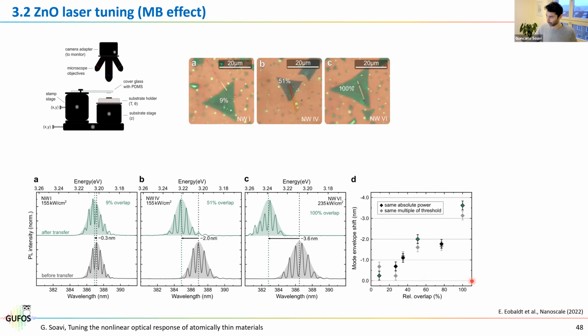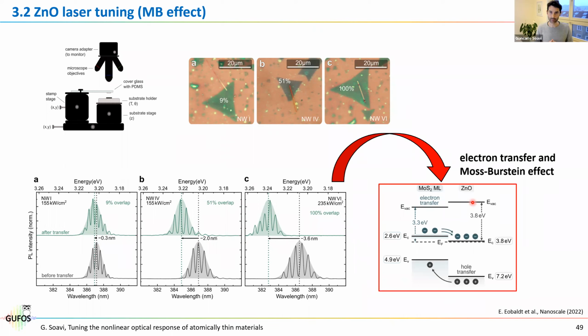Now you can plot the mode shift as a function of the relative overlap of the nanowire and the TMD, and you see that there is this monotonic increase. We were wondering why this happens, and our assumption is that this is due to charge transfer.